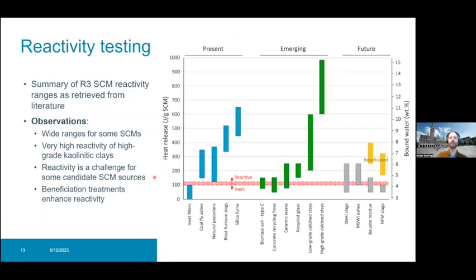Going back to the R3 reactivity test, the summary perhaps shows that for these groups of materials that we introduced before, present, emerging, future SCMs, here we scale from inert fillers to silica fume as a very reactive material. But it's also interesting to see where these new materials plot. So biomass ashes or concrete recycling fines are typically on the edge of being reactive or not, while calcined clays have very high reactivity depending on their kaolinite content. High-grade kaolinites are very reactive materials. That's clearly shown in these test methods.